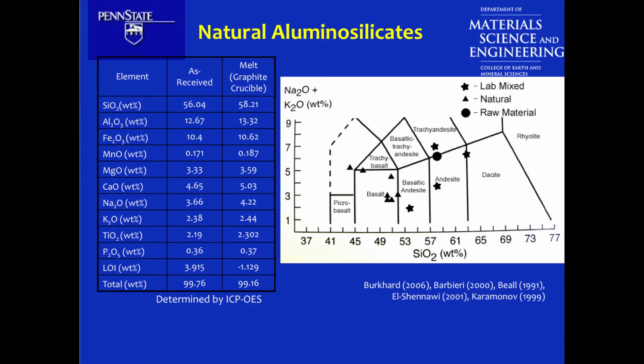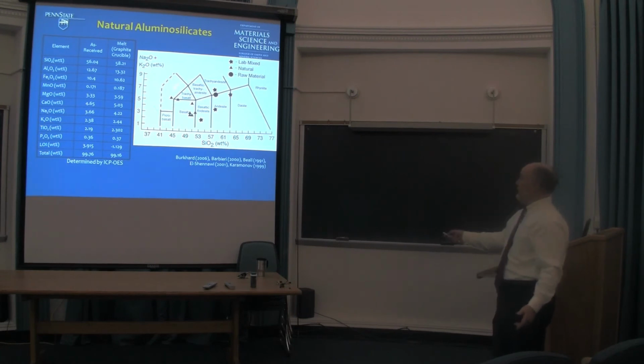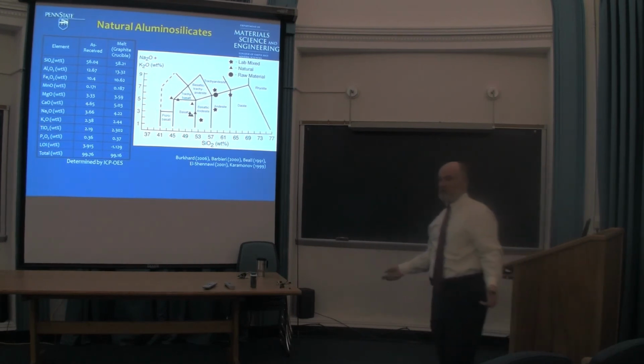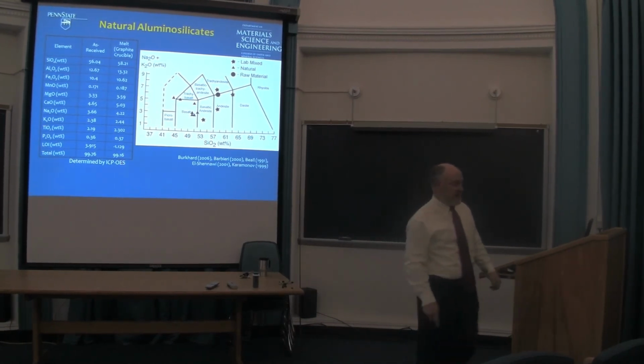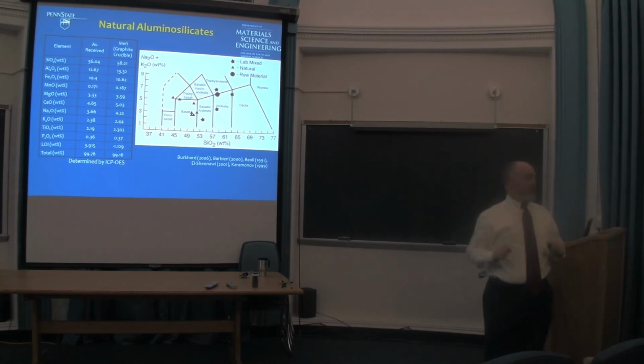Well, in the glass case, I'll tell you about the aluminosilicates first. So in the aluminosilicate case, we said, fine, use those mine tailings that are going around here someplace, that green stuff, manufacture glassy beads out of that using a flame spheroidization process, then using what we know from 80 years worth of glass ceramic research, devitrify that glass to give you the right crystalline phase assemblage and microstructure to increase the fracture toughness of that bead to the point that it fails into big particles. Well, we can do that with the materials that are mine tailings because they have the right alumina-silicon ratio as well as the alkaline and alkaline earth content for us to have a pretty good idea where we have to heat treat this stuff to make glass ceramic that'll have some altered mechanical properties.